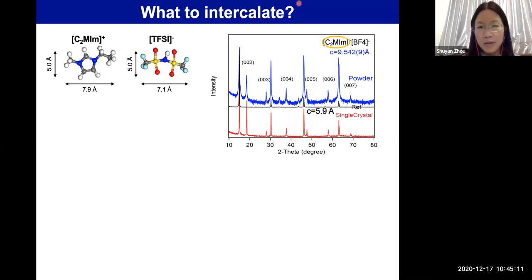So how do we know what kind of ions we intercalate? We use an electrochemical method to intercalate the sample, and to confirm the intercalation, we use X-ray diffraction. So here I show you data measured on the single crystal sample with an interlayer spacing of 5.9 angstrom. Now, after intercalation, the interlayer spacing increases to 9.54. And so this is using one ionic liquid.